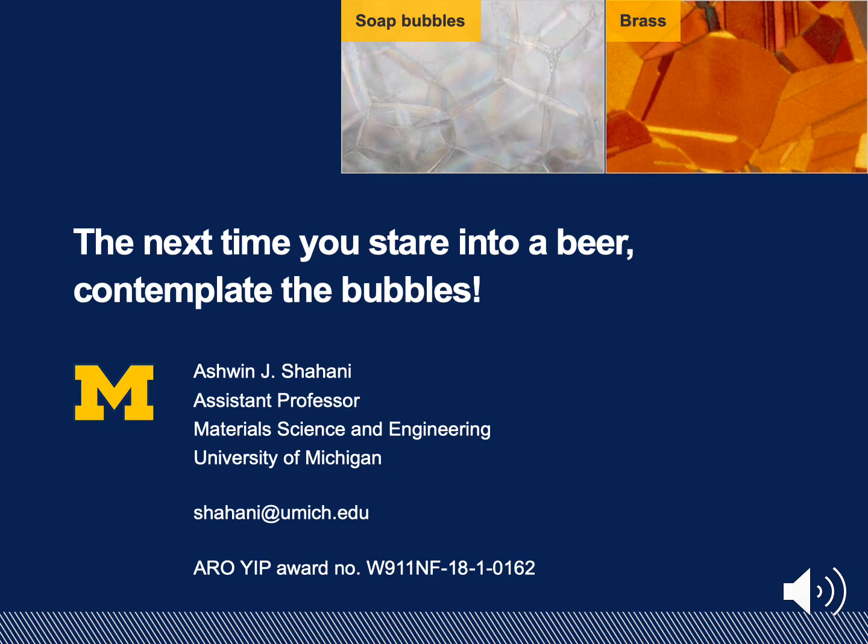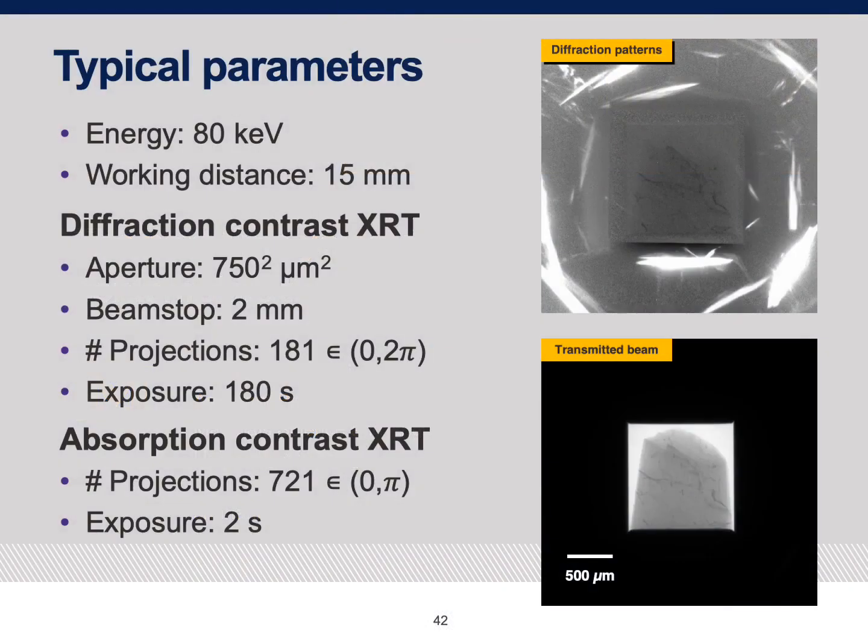And this allows us to identify approximately 80% of the grains from one time step to another and track their evolution. So we have now achieved grain level resolution. We can now track the same grain across many different time steps. Of course, 80% is pretty good because some grains will disappear due to the coarsening process, right? And of course, some grains will enter the field of view because you have an open system. This is a long rod, which will only illuminate a section of it. So 80%, I would say, is pretty good.